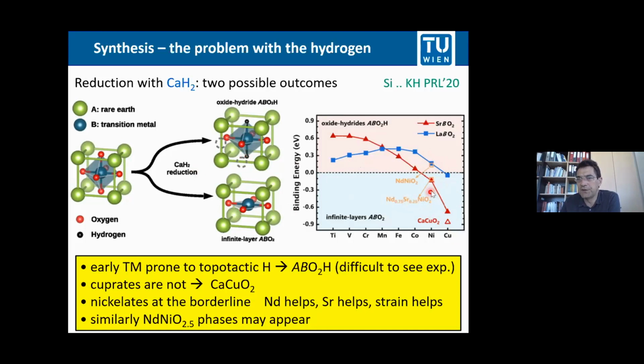But if you dope it with strontium, the fully strontium nickel O2 in red, but also the 25% doped system, they prefer the infinite layer structure. But that tells you that, at least for the lightly doped nickelates, you have to watch out. You have to watch out that there might be hydrogen in the system. And the problem with the hydrogen is you don't see it in standard experiments.